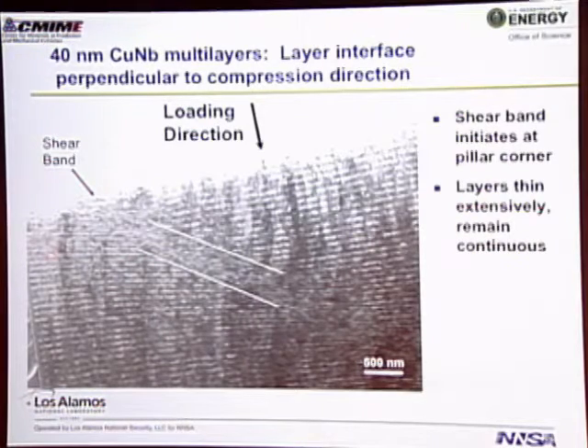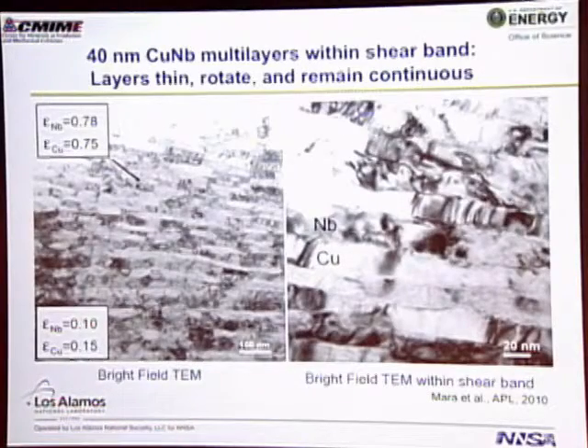And what you see is if you start on one side of the band and go to the other, it's continuous across the entire shear band. We can look at it closer, increase the magnification. Here's our band again. And if we look at an area like this even closer, here's our band. The copper and niobium doesn't break up. It's still strong. So the question is, how is it softening? Well, one thing that could be happening is if the interfaces can slide like a deck of cards, that would make sense as to why this material gets softer as we form this band.